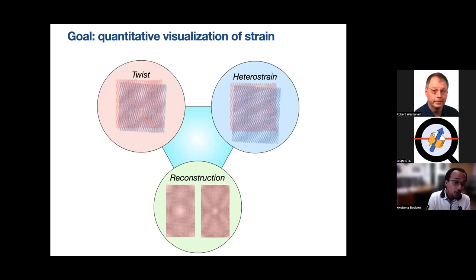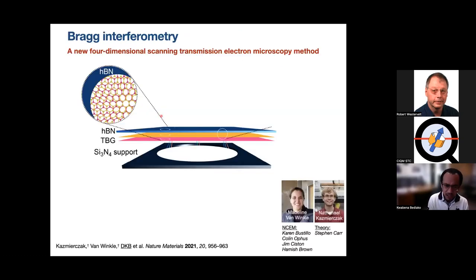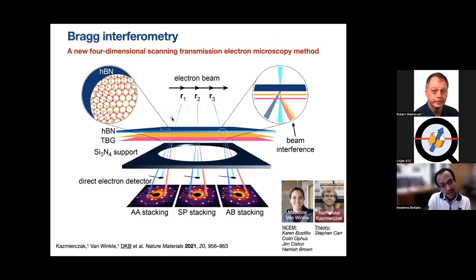And so the goal we had, which helped us to understand the chemistry we were seeing, was this quantitative visualization of strain and this interplay between twist angle, heterostrain, and relaxation. And the tool we used to do that, to take these measurements, is called four-dimensional scanning transmission electron microscopy. And this is a technique where we take an electron beam, we converge it, and scan it over the sample, right? And scan it in two dimensions, in Cartesian coordinates and sample, and then we acquire a diffraction pattern at each probe position, where maybe each probe is separated by anywhere from, let's say, 5 angstroms or 10 angstroms or less from each other.